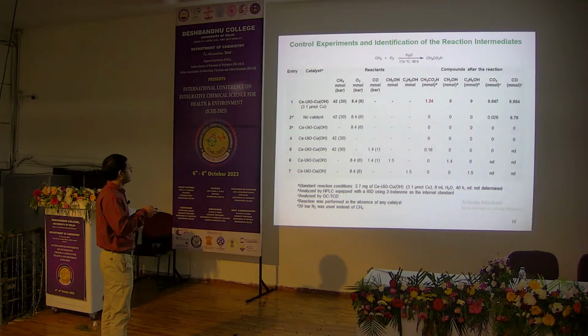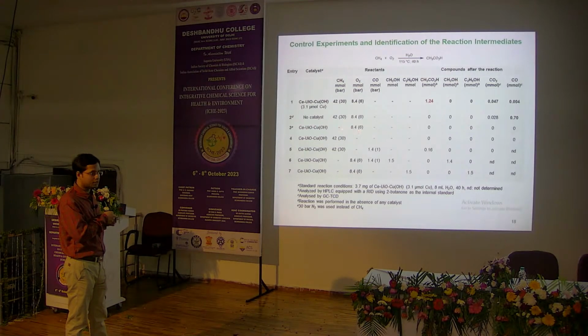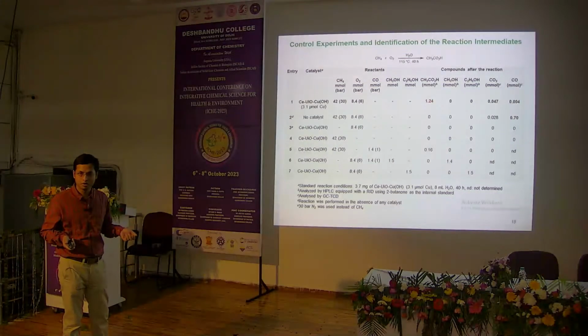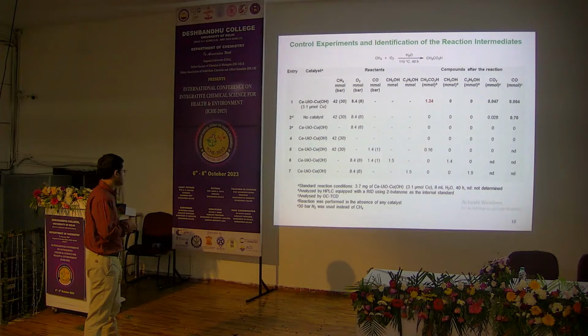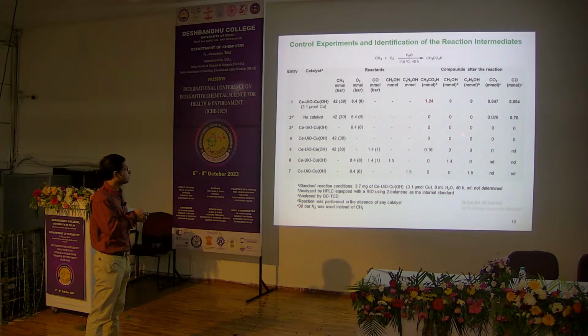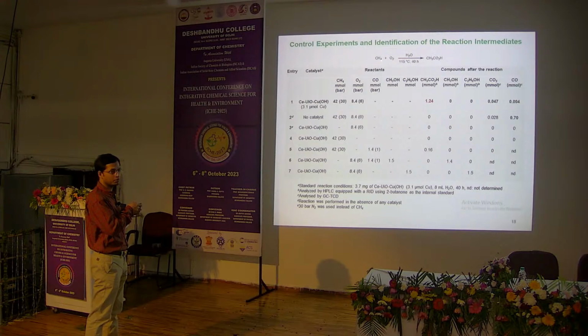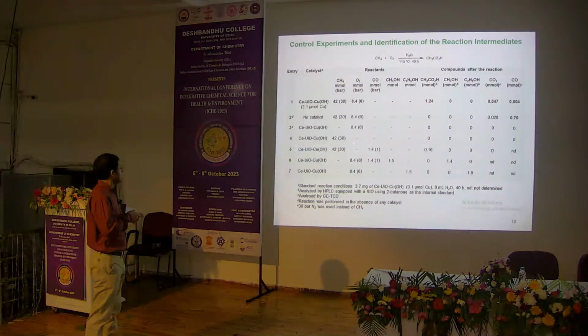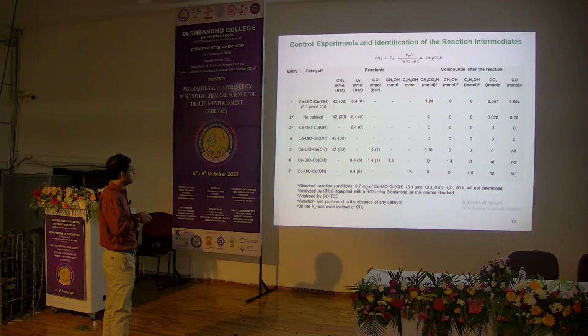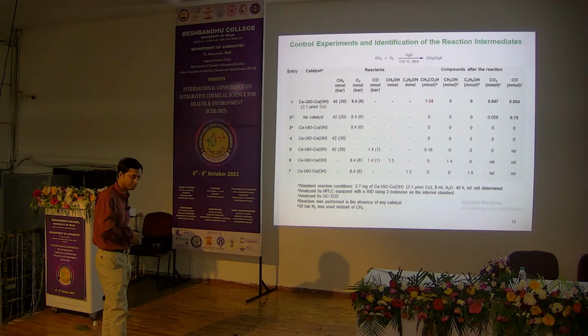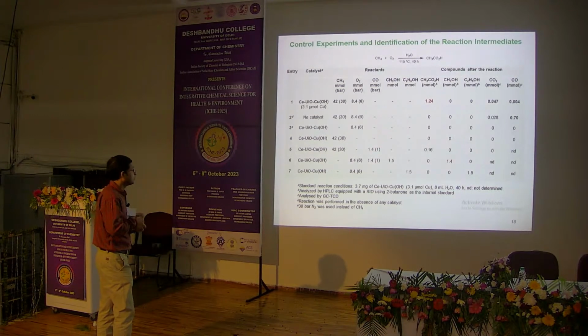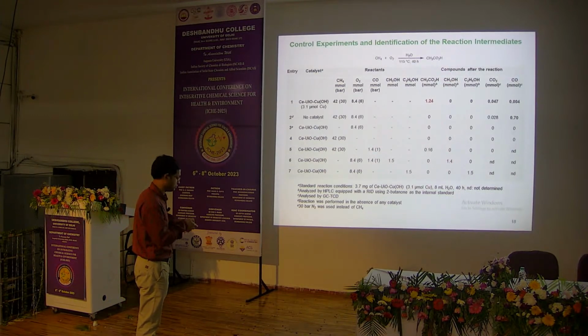We did a lot of control experiments. First of all, if you do the oxidation reaction in the absence of catalyst, there is no conversion. That indicates that for methane to acetic acid, we need the catalyst. If you do the catalysis in the absence of methane, in entry number 3, there is no product. That indicates that the carbon source in the acetic acid is actually coming from methane, not from anything else, not from the material. Also, if we do the catalysis in the absence of oxygen, there is no catalysis occurring. Another interesting thing is that if we use carbon monoxide instead of methane, entry number 6, then we also didn't get acetic acid. But instead, we got a small amount of methanol.